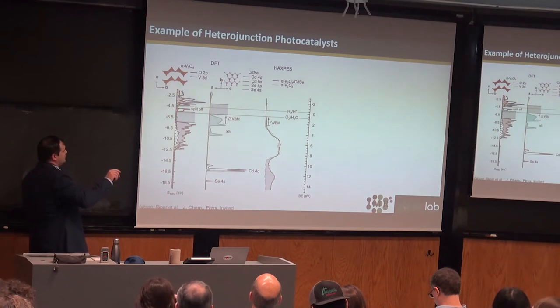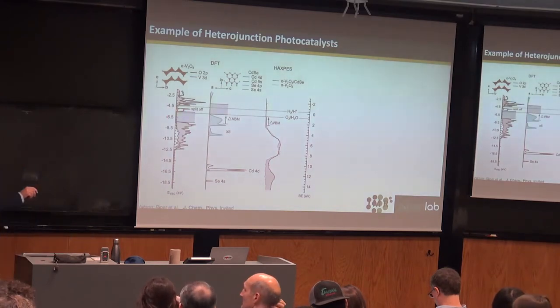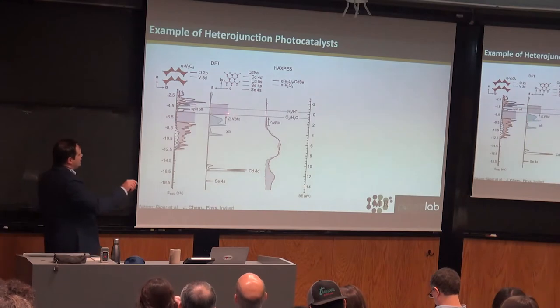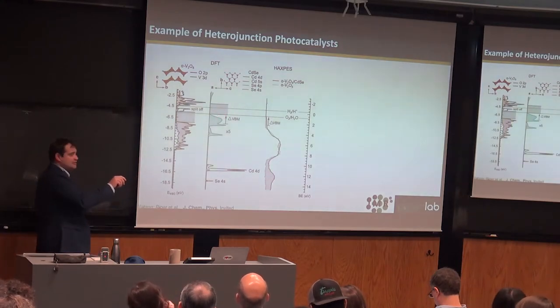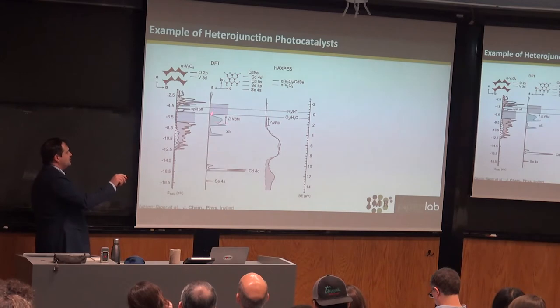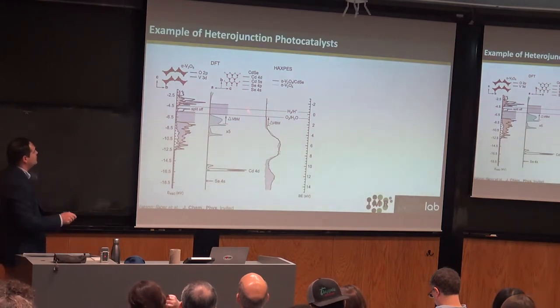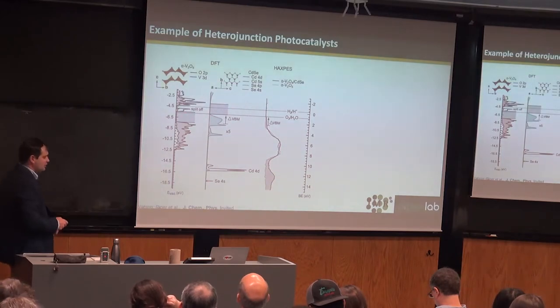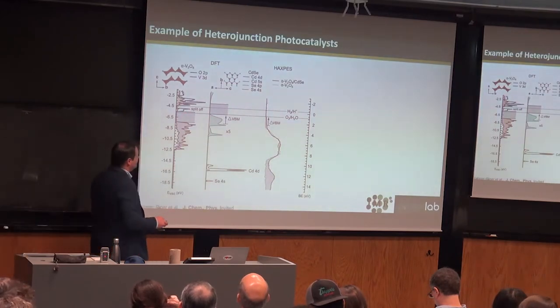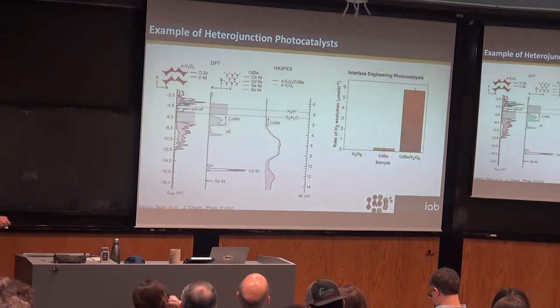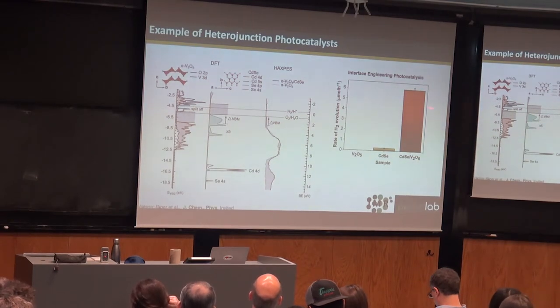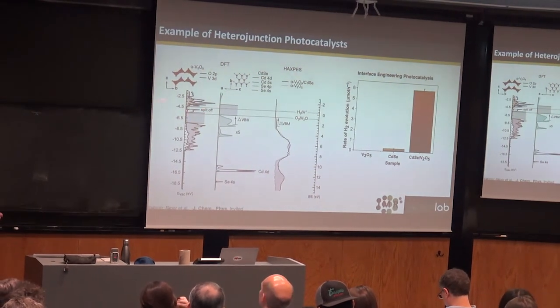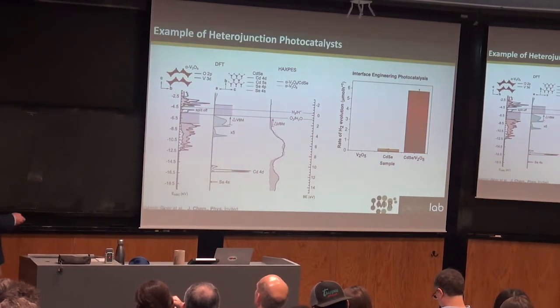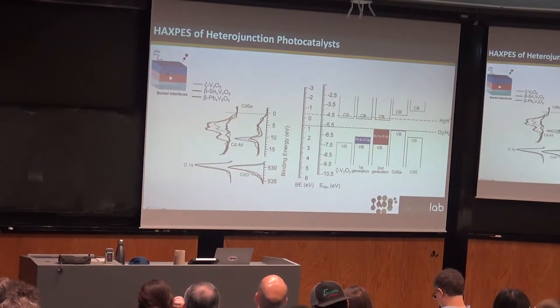They'll get localized in the split-off band, and that's good for the photochemistry for the hydrogen evolving, but you get a buildup of holes on this side. So you need to have sacrificial carriers to deal with the buildup of holes that lead to photocorrosion. So this direction of how the charge is separated is not good for our design, although it does show how you can take two systems which are pretty poor and introduce better hydrogen evolving behavior from that. In that case, the hydrogen is being evolved on the V2O5. So the idea is, can we switch that around?